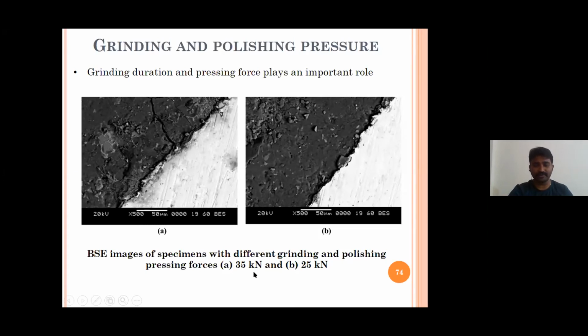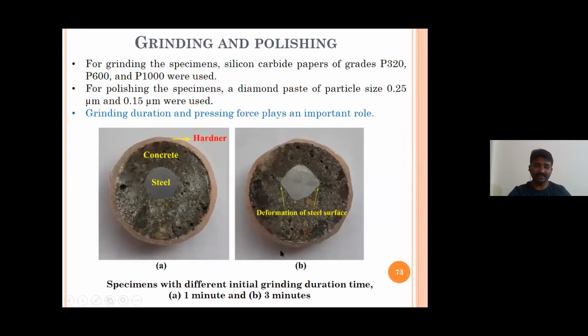We tried with 35 kilonewton, which was mentioned in previous papers. But for 35 kilonewton, there are a few cracks we could observe in our SEM images. And see this one, there is some distortion of the steel surface. If you could observe my cursor, there is some amount of distortion here, and a few cracks are also there. That is for 35 kilonewton force. Then I reduced it to 30, and then to 25. See, for 25, the distortion of steel is very little, but at least I have to keep 25 kilonewton to observe the best SEM images. So from this, we have concluded that the force should be 25 kilonewton and time should be at least 1 minute, and should not be more than 1 minute.